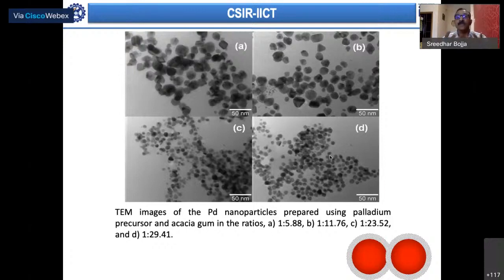When we try to understand this, the reason is the steric hindrance on the growth of the nanoparticles is less when the concentration of gum is less, which means it allows the particles to go bigger. But as the concentration is increased, the hindrance on the growth of the particles is also increased, and that limits the size to 8 to 10 nanometers, which are also uniform in size. So that is how concentration also influences the particle size.